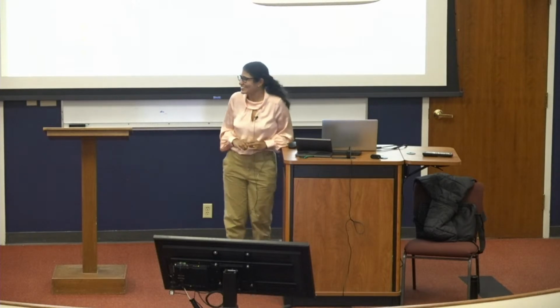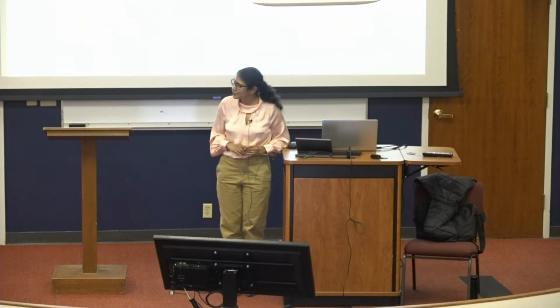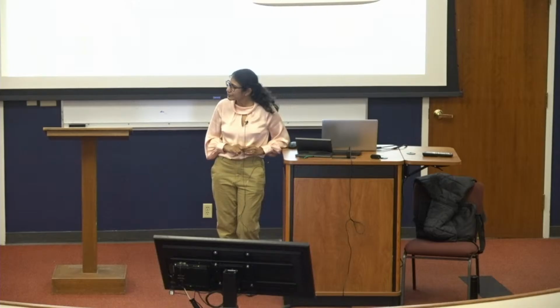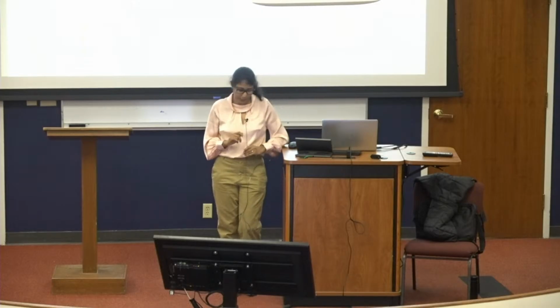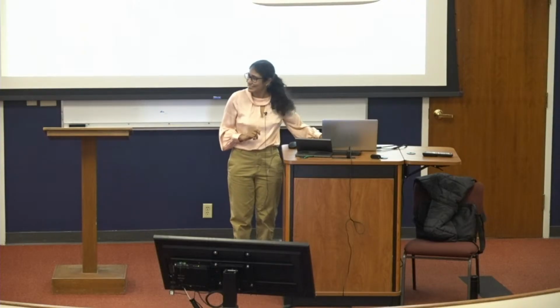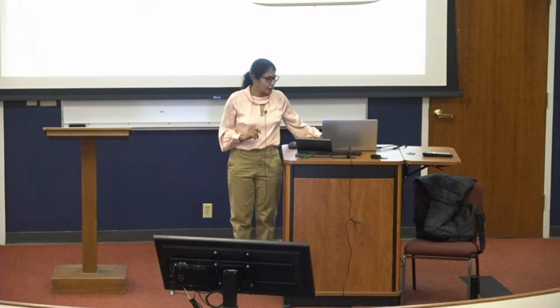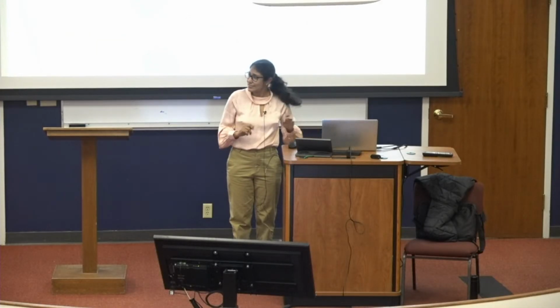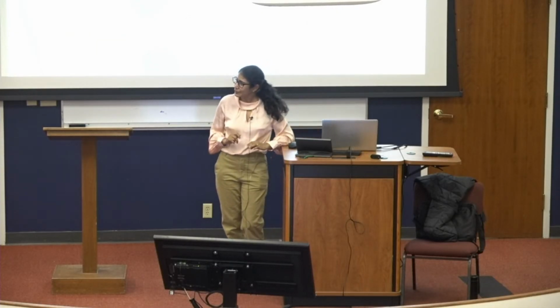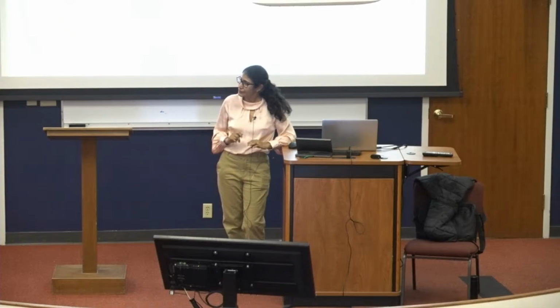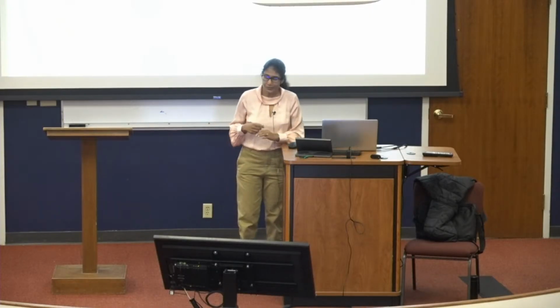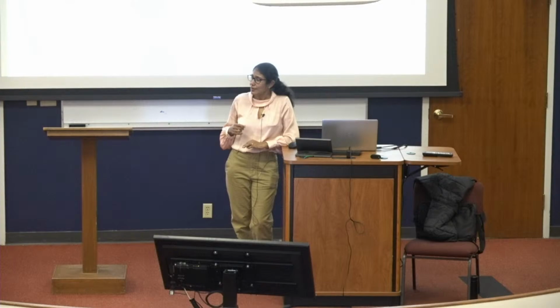On the metal corrosion study, you showed a small table that extrapolated the thickness of the metal that would be lost in a year for the coated versus the uncoated. You measured it after 21 days in the salt solution. Could you talk about how you measured that thickness loss? And over how many samples was that average that you gave us?